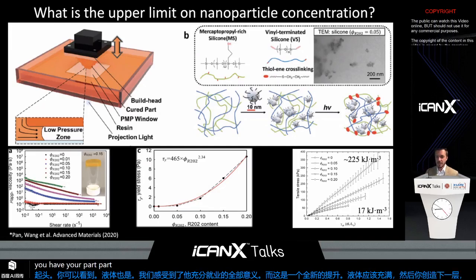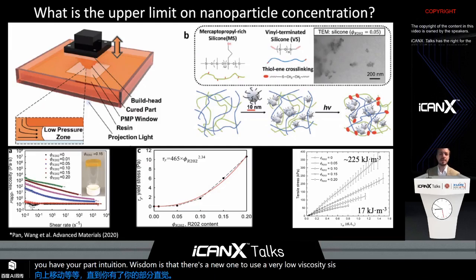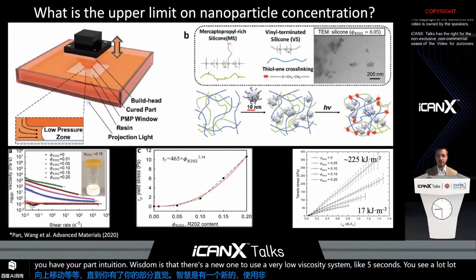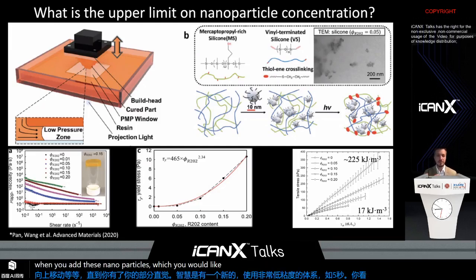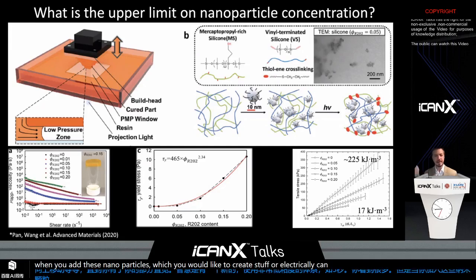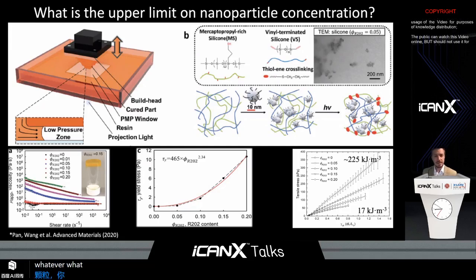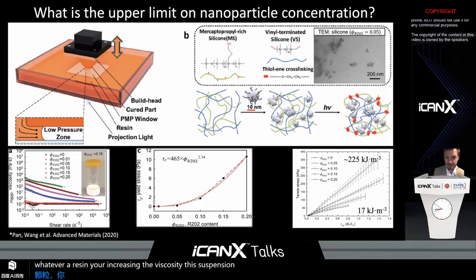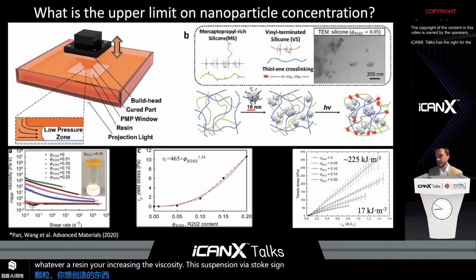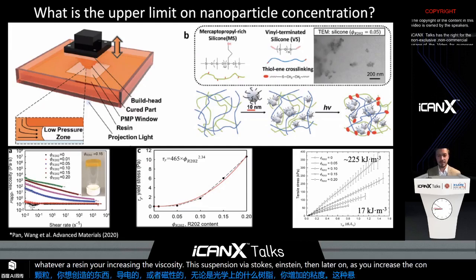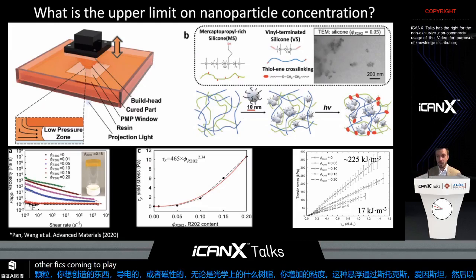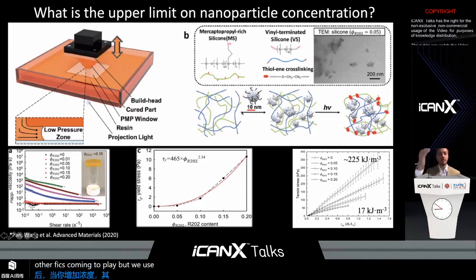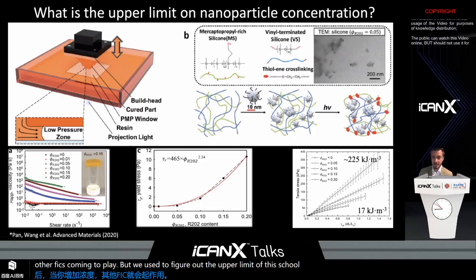And traditional wisdom is that you want to use a very low viscosity system, like 5 Pascal seconds. But when you add these nanoparticles, which you would like to create tough or electrically conductive or maybe magnetically or optically active resin, you're increasing the viscosity of this suspension via Stokes-Einstein, and then later on, as you increase the concentration, other effects come into play. But we wanted to figure out the upper limit of viscoelasticity for these nanoparticle suspensions.